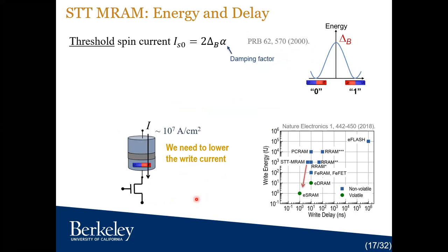So let's look at the physics, like what's stopping us from lowering the write current. As I mentioned, for STT, you need to have at least a minimum amount of spin polarized current to switch it. And that threshold value is given by this expression. It depends on the anisotropy energy, which separates the 0 from 1. This determines your memory retention time. So for a particular technology, this is fixed. You cannot change it. So the only parameter that you can play with is this damping factor.